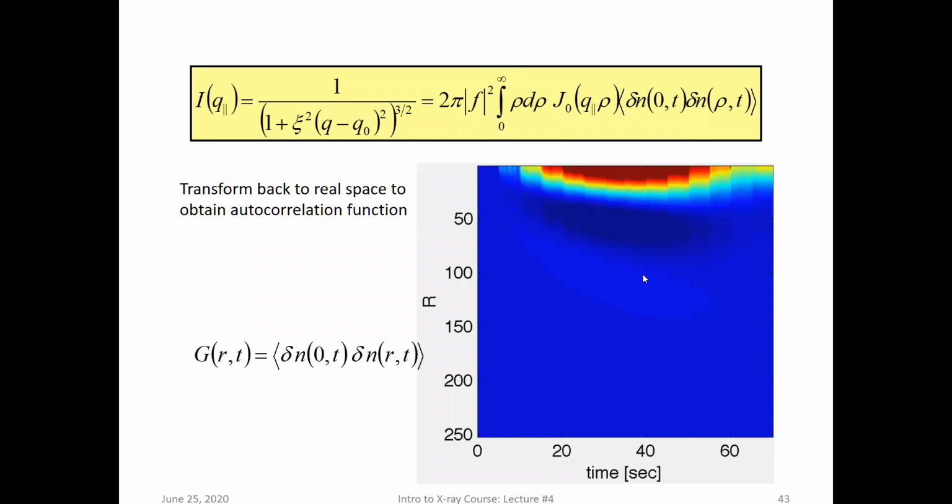So we've now been able to actually image the way the islands behave. This goes away because there are no islands out here or here. And something interesting happens here, right? These are fluctuations. Here the island is growing, we're adding material to it. The island doesn't really shrink. What happens on this side is that what we're really looking at are holes, little hockey puck shaped holes. Here we have hockey puck shaped islands.